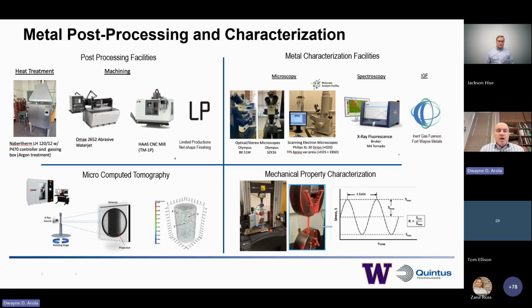Next thing we're doing is evaluating porosity distribution within the metal, within each of the zones that was produced and for each of the partners. After understanding microstructure, we'll move on to fatigue, cyclic loading, which I'll describe in just a little bit. And then after we have components that fail, we're evaluating fracture surface morphology, identifying root cause or the origin. That's done 100% for all our failed components.